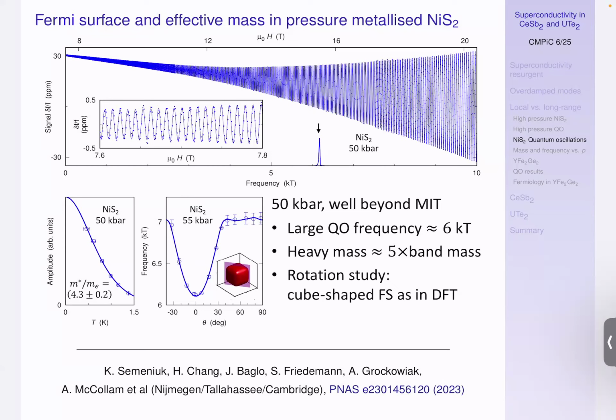And you can look at the angle dependence of the frequencies of these oscillations. Because the oscillation frequency tells you the cross-sectional area of the Fermi surface. That angle dependence gives you a way to figure out the shape of the Fermi surface. And it turns out to look like a little cube, which takes about 1/3 of the volume of the Brillouin zone, from what I remember. And it basically is consistent with exactly what you would get from a DFT band structure calculation.